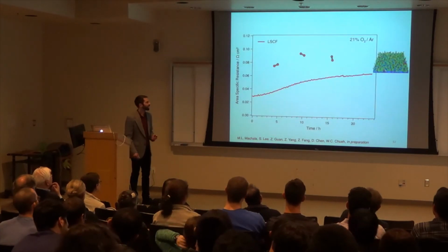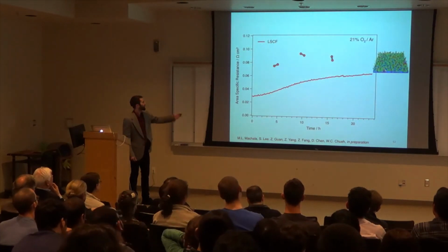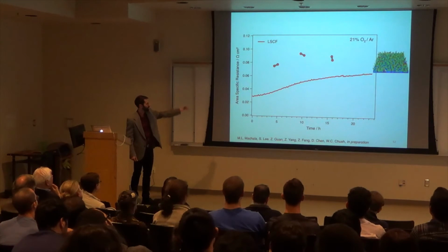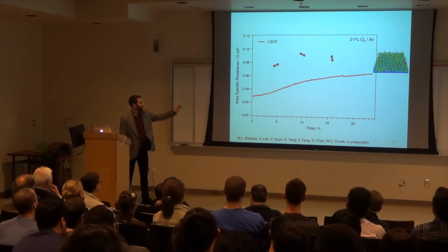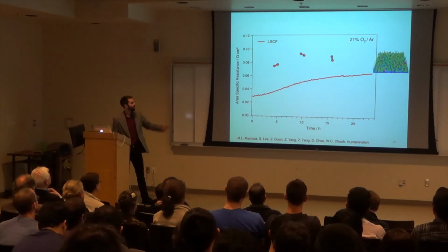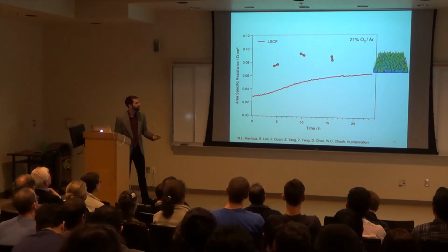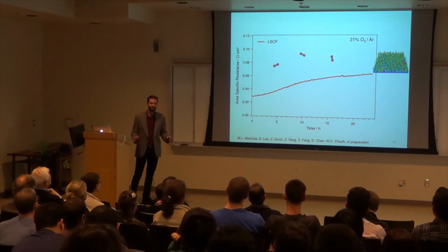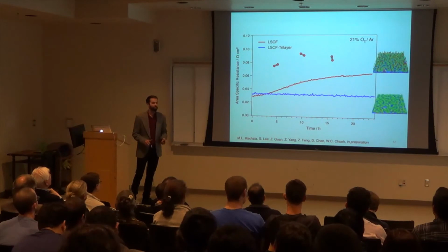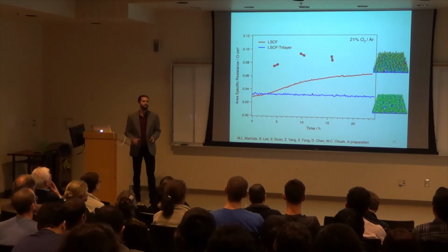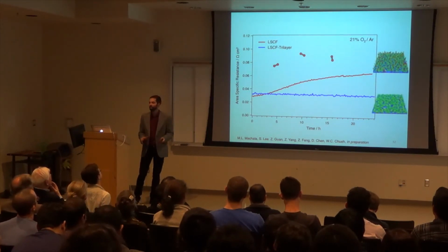So, let's take a look at what the degradation looks like, actually. Here's the resistance on the y-axis, a function of time for 1 day. The LSCF, without the trilayer structure, you can see that it degrades over time. Now, what's exciting is when we actually tested the trilayer structure, it was relatively flat. We didn't really see much degradation at all.